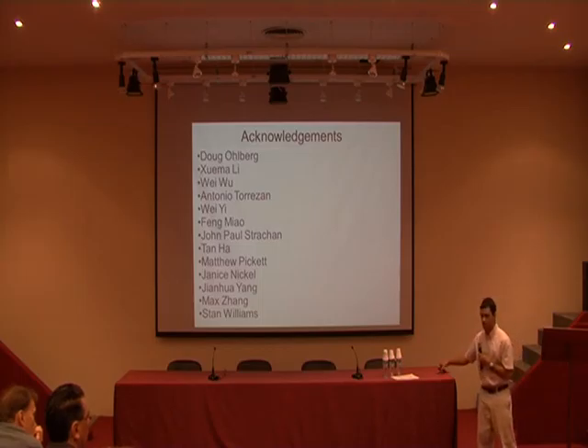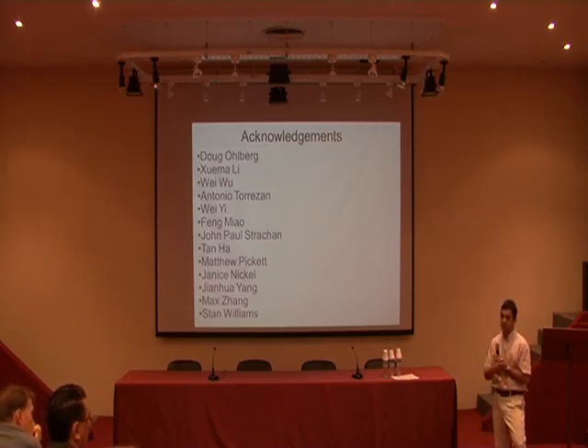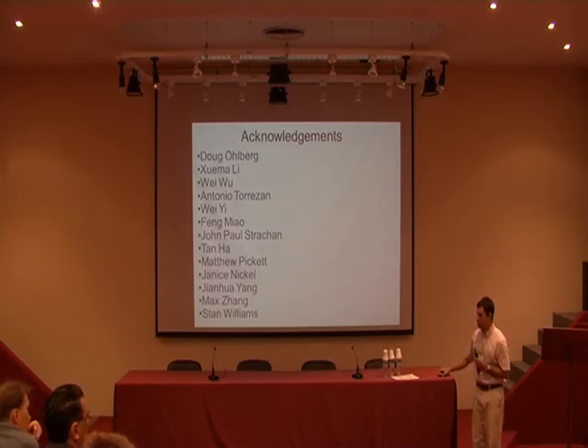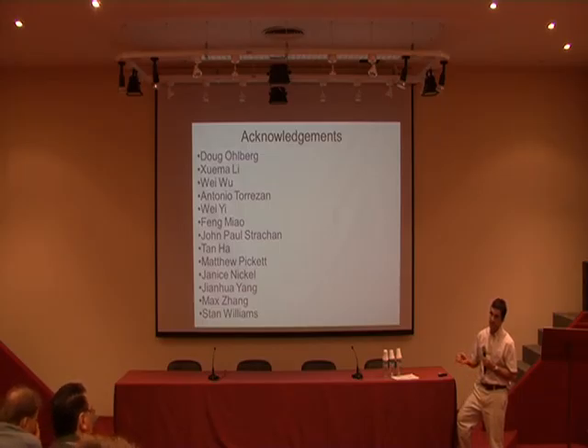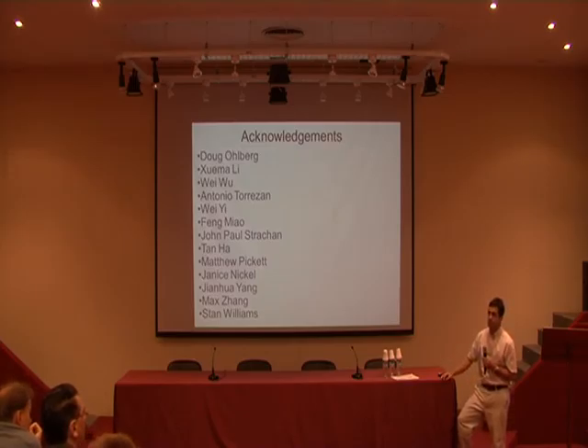Now, I gave the example of titanium oxide and vanadium oxide, but there are others, for example, niobium oxide. My colleague Matthew also published a paper on vanadium oxide, and I think there was a question yesterday from you, how long does it take for that transition to take place? In his paper he used the same high speed setup, and he was able to show 500 picoseconds or something like that. But I think it's more like a thermal effect than the actual phase transition. The phase transition is actually faster than that.